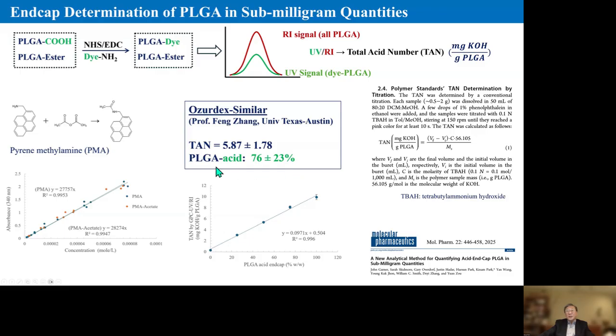In terms of percentage, how much PLGA acid is present in Ozurdex? By the way, Ozurdex itself was not available for research use because the manufacturer did not sell it for research. So instead, we used an Ozurdex-similar formulation, made with exactly the same method that Professor Feng Zhang prepared in his lab. When we assayed the amount of acid, it turned out to be 76% plus or minus 23%. So it's close to the 75% he added in when he made the formulation. Now, the large variation is due to the use of an extremely small sample quantity. Whenever we pick up a small amount, it may have some variation. But overall, if you measure enough times, the average becomes the same as the original 75%.